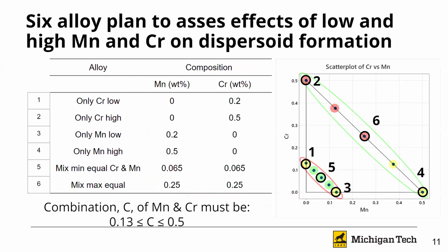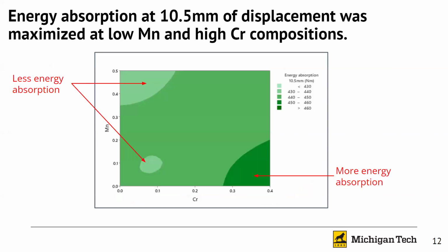From this, we designed an experiment to test the energy absorption of six of the compositions that we ran in the simulations. And we found that the high chromium and low manganese compositions yielded the best energy absorption. Our samples were too thin to get bend angles from the VDA test, so we used the area under a force versus displacement curve to 10.5 millimeters of crosshead travel to normalize our results.